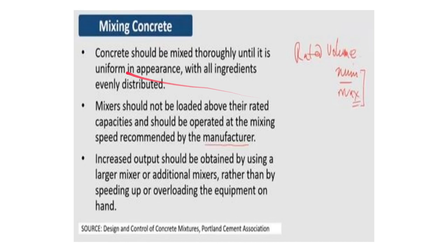If we go to mixing concrete, concrete should be mixed thoroughly until it is uniform in appearance with all ingredients evenly distributed. Mixers should not be loaded above their rated capacities and should be operated at a mixing speed recommended by the manufacturer. Increased output should be obtained by using a larger mixer or additional mixers rather than by speeding up or overloading the equipment on hand. That will damage the equipment, and it will also result in an improper and non-homogeneous mix.